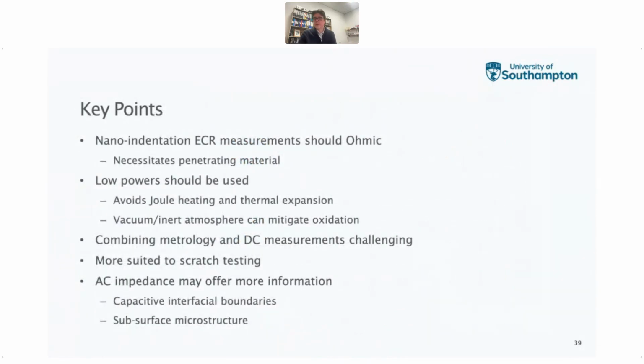All right, so just to summarize the key points, I think. If you do nano-indentation measurements using electrical contact resistance, really being in the ohmic region is preferable to avoid any of this ballistic resistance terms that you get, and that necessitates penetrating the material. You really ought to probably use lower powers if you want to avoid any dissipation of the Joule heating into thermal expansion of the material. And if you want to also mitigate surface oxidation, using an inert atmosphere or a vacuum environment such as that you might find in a scanning electron microscope is also useful.